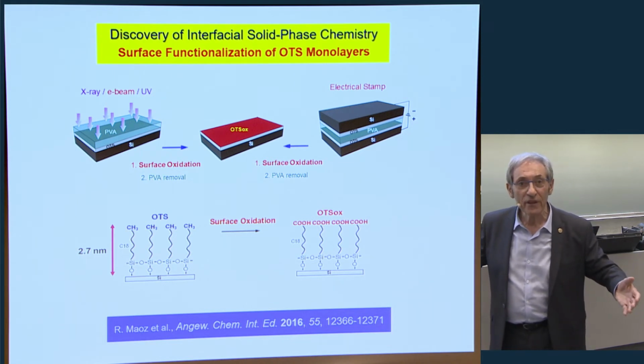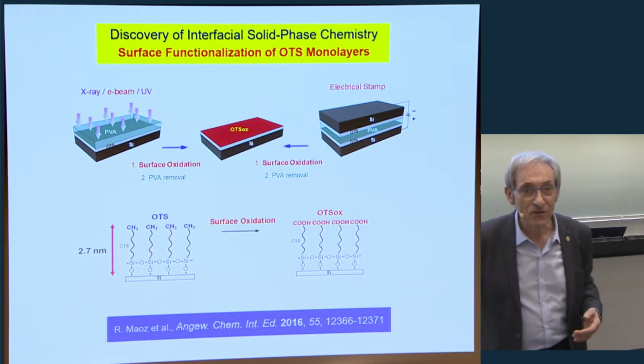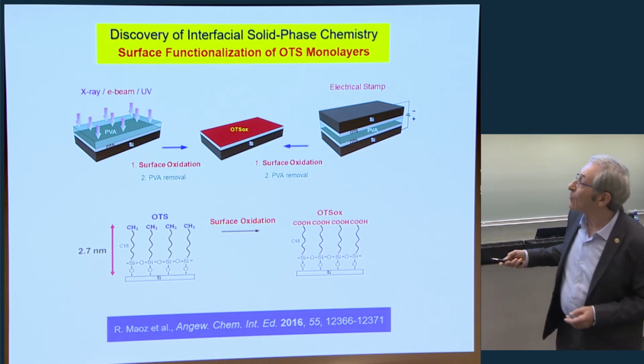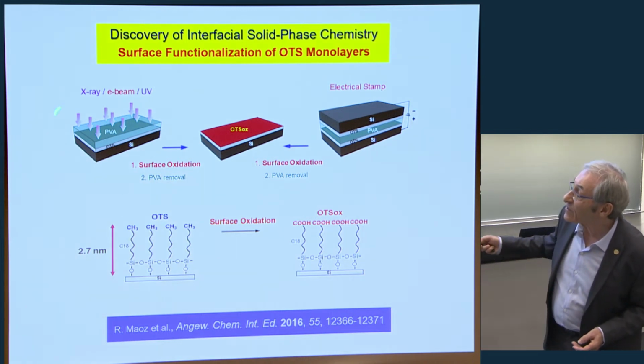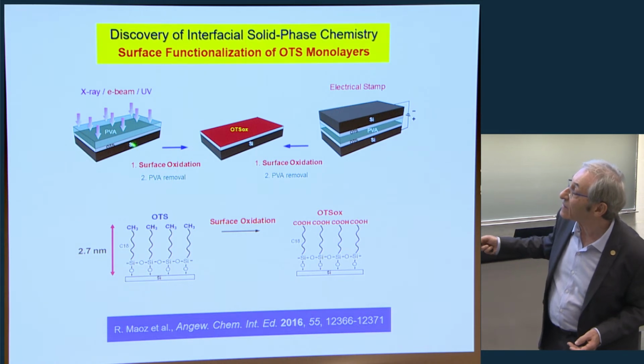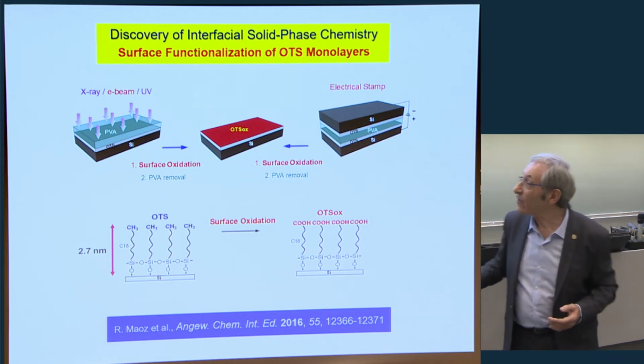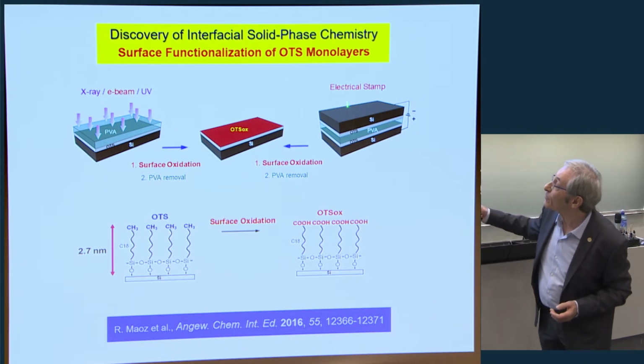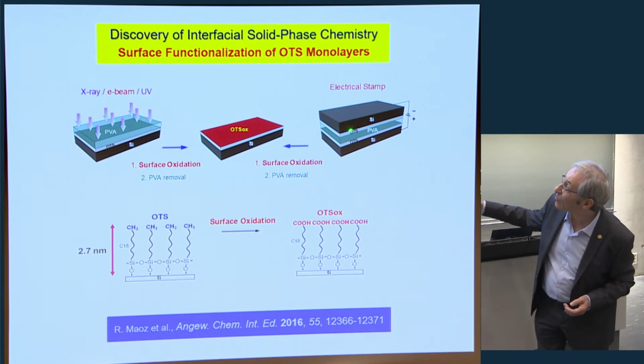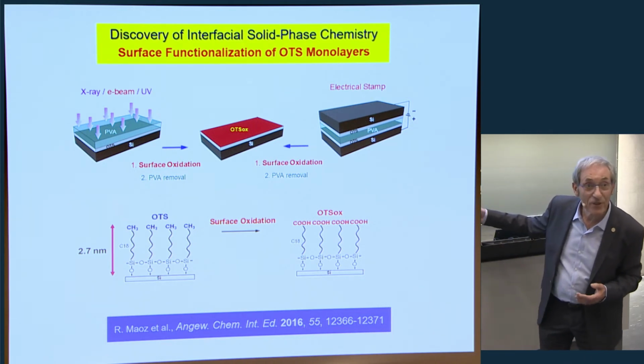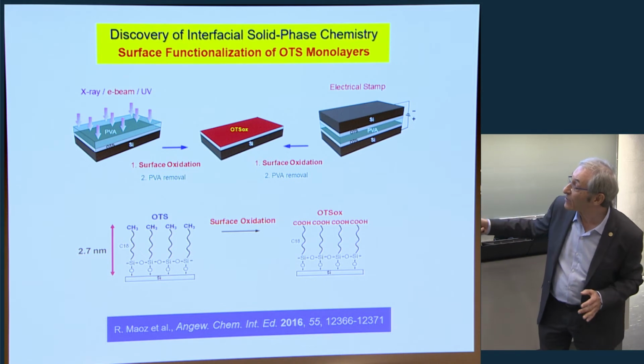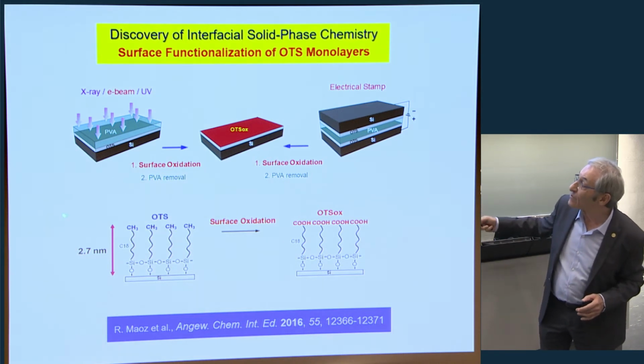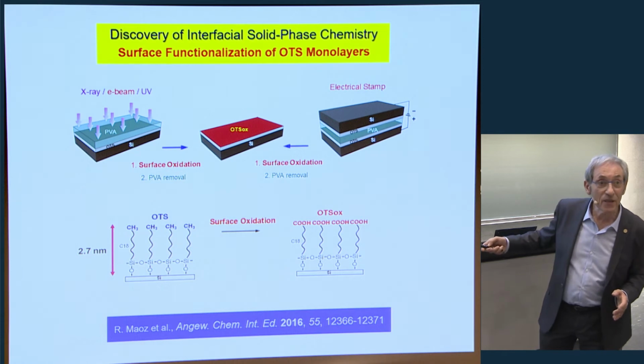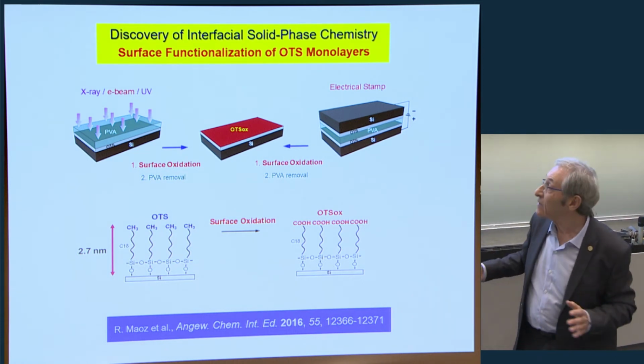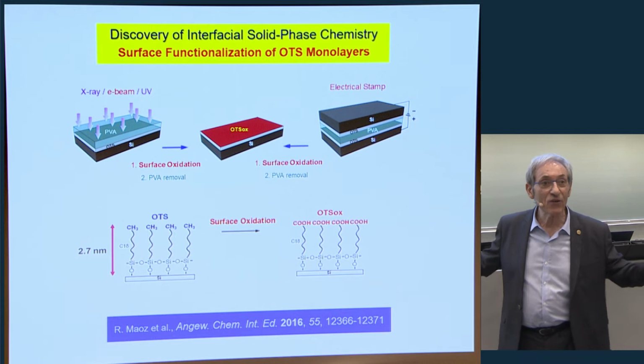Polyvinyl alcohol is a polymer that contains OH groups, and it's very popular in many applications, also in cosmetics and so on. So it turned out that if you have this sandwich and we irradiate it with either X-rays or electrons or UV at short enough wavelength, or you place a similar OTS monolayer, which is an electric stamp, and apply a bias, both work equally. It is again possible to convert the CH3 to carboxylic acid while preserving the structure of the monolayer. This is extraordinary because here we don't need any longer a liquid.